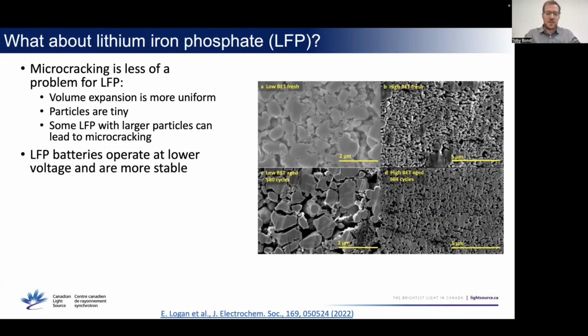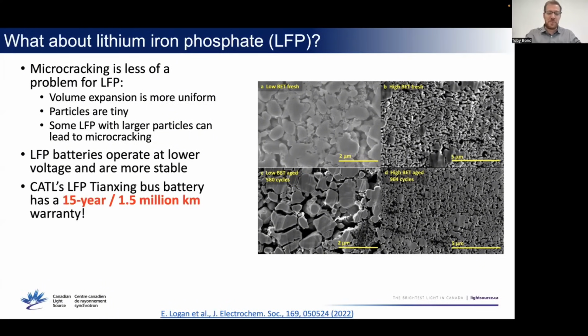The reason you can have these tiny particles is that LFP batteries are much more chemically stable. They operate at lower voltage, and so they don't react as much with the electrolyte. And so you can actually have these tiny particles to start with and have all this extra exposed surface area, and it's not as big of a deal. And so LFP, I should mention, because of this, it's got really, really good lifetime as well. It just doesn't have as good energy density.